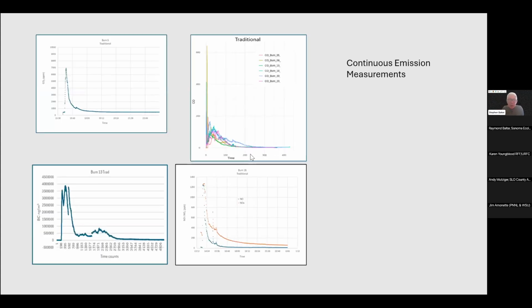Here's a look at some of the continuous emission measurements, which are pretty similar to the field. These aren't aggregates like we saw before, except they're for one individual fire. Looking at the CO2 on the left, you can see the concentrations that we were measuring up on the platform were quite a bit lower than what we got in the field. You see 7,000 ppm for CO2, and we were looking at 25,000 ppm for CO2 in the field.